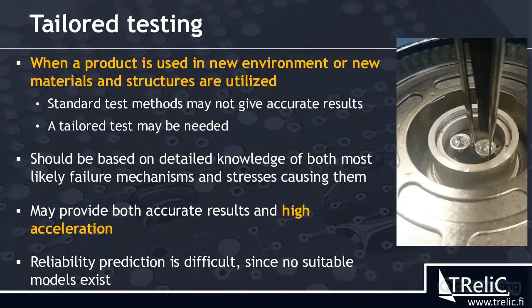Then last about testing is tailored testing, which is kind of a trend, has been for some time now in reliability engineering. So the idea here is that we tailor the test according to the product. So instead of taking a ready-made standard test, we actually design the testing according to the product using mission profiles and so on. The good thing about this is that we can have very accurate results if we know the conditions, but this testing may be very demanding to design and to do if we do combination of several stresses. But this may also give us very high acceleration without the problems related to HALT or HAST. So we are still dealing with realistic failures.